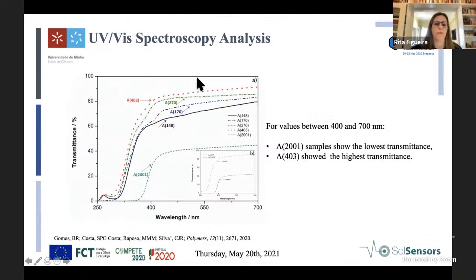So when we used ultraviolet-visible spectroscopy analysis, we saw that the transmittance changed with the different jeffamines. You can see that the samples prepared with jeffamine ED 2001, we name it A because the type of bond established between the jeffamine and the GPTMS is an aminoalkyl bond, showed the lowest transmittance, and the one with the highest transmittance is A403. As you can see here, this is the lowest transmittance and this is the highest transmittance.